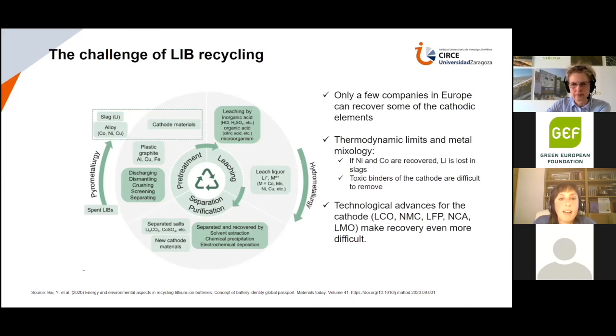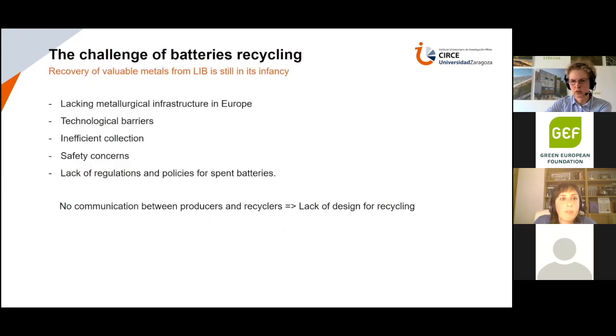just because it is not designed for recycling. And another important barrier is that because of technological advances, because we want to reduce the consumption, for instance, of cobalt, which is very critical, we have different configurations of cathodic materials. So we have LCO, NMC, LFP, NCA, LMO, etc., that were explained by Thomas. So recyclers get a mixture of materials and they do not really know what they have in that mixture after the crushing processes. So this becomes even more difficult for the recycling process.